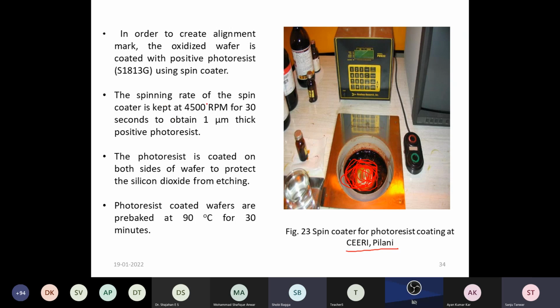The spin rate of the spin coater is kept at 4500 RPM for 30 seconds to obtain a 1 micrometer thick positive photoresist. The photoresist is coated on both sides of the wafer to protect the silicon dioxide from the etching. Why photoresist? By coating it, the oxide underneath will remain intact.